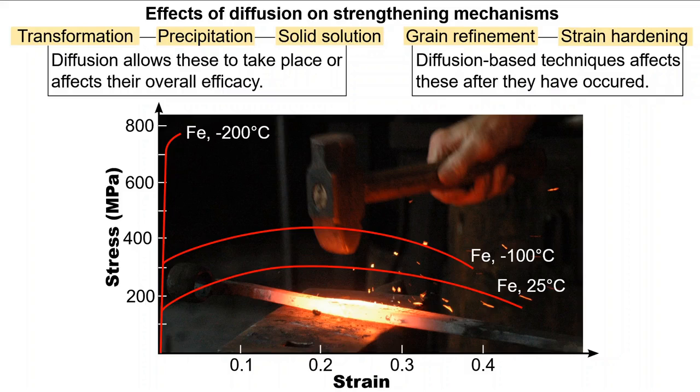If diffusion is denied, then there is diminished ability for phase changes to occur, at least as described by equilibrium conditions. When developing precipitates by aging processes, the longer at an aging temperature will evolve larger precipitates, which may affect the overall dislocation dynamics. For solid solution strengthening, denying an even distribution of alloying ingredients will also do the same.